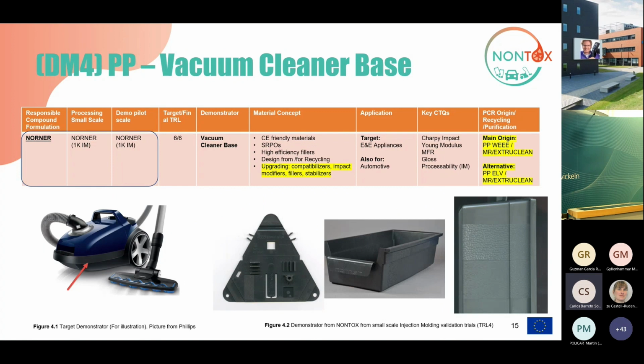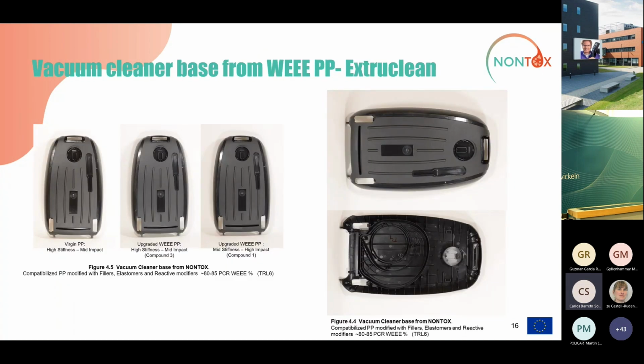The last two are about those that really came to TRL 6. The target here was a vacuum cleaner base based on polypropylene from WEEE that was devolatilized by Extruclean. The upgrading was towards improving the stiffness and the impact, while still remaining inside the density of 1 to fit the sorting by density. It was a quite interesting activity where we managed to develop a material that was pretty close to the virgin polymer with an 85% recycled content, and one with enhanced impact with a really high value of Charpy, but still compromising the stiffness.